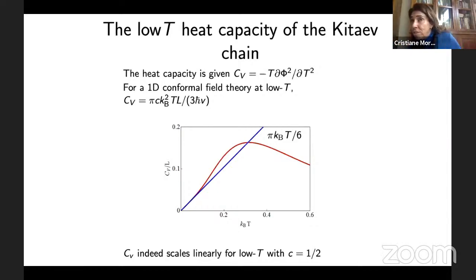You have some fluctuations. How are your fluctuations? It depends on how close you are to the critical system, because of course, as you get closer and closer, your gap gets smaller and smaller. That is true, but you get much more quantitative results if you do that. As for instance here, I can show you, I can extract the central charge of the heat capacity by doing calculations at finite temperatures. It is always very useful to understand how the behavior is at finite temperatures. The intuition that you simply should have KBT smaller than the gap is more like an order of magnitude.